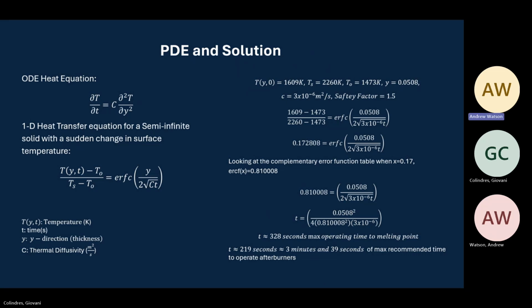Through plugging all those variables in and calculating, we were able to find that the max operating time before we hit the melting point of Inconel would be 328 seconds. When we added a safety factor of 1.5, that brought it down to t equals 219 seconds, which is 3 minutes and 39 seconds, our max recommended time to operate the afterburners. Next.